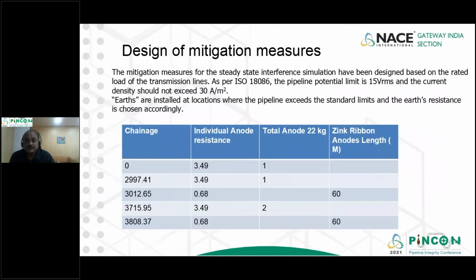For the steady state interference simulation, it has been designed based on the rated load of the transmission line as per ISO 18086. The pipeline potential limit is 15 VRMS, and the current density should not exceed 30 amps. Between these chainages, we figured out that the total anode requirement was 4 anodes of 22 kg each. We have installed them in these chainages.